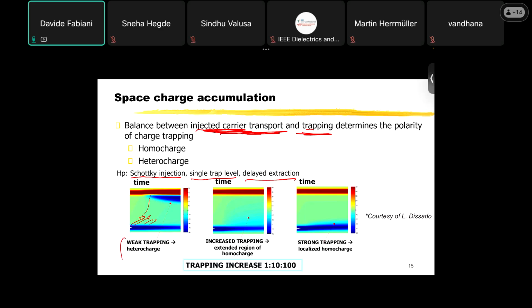creating heterocharge. And I told you that this is very dangerous, no? When you have heterocharge. But if you increase the trap depth inside the material by a factor of 10, you see that there is a more extended region of homocharge that does not reach the counter electrode very easily because the traps are much deeper now. And if you increase the trap depth further by another factor of 10, what you can see here is that you have only a very thin layer of homocharge close to the negative electrode. So you don't have heterocharge anymore.